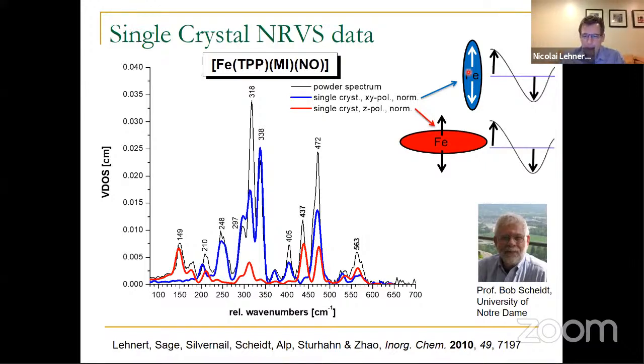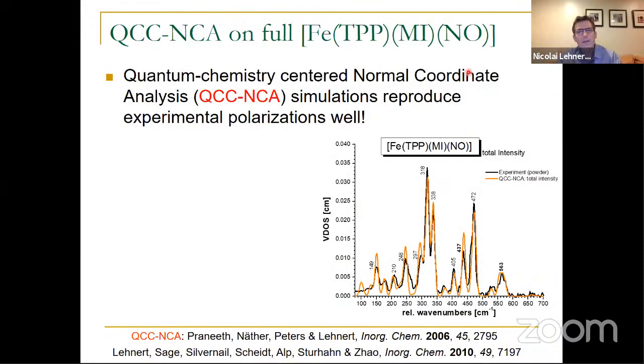But in order to get this further, we have to also simulate the data. So we can use our quantum chemistry-centered normal coordinate analysis. Normal coordinate analysis is the standard method of simulating vibrational data using a force field. And because there's a very simple relationship between intensity and the properties of your normal mode, we can actually simulate spectral intensities here as well. So we worked very hard, and you can see here we were able to fit the data.